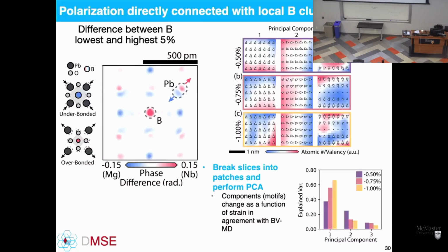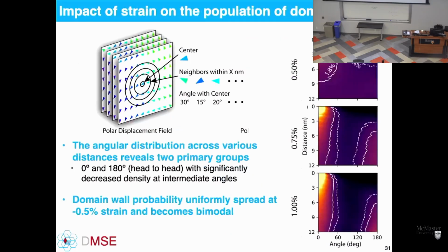And doing polar principal component analysis, for example, allows us to, in a statistical way, look at how these polar motifs, if you will, change across a sample. And as you increase in strain, you become more polar along a single direction, whereas the 0.5% strain, lower strain states, still preserve more of the sources of polarization that you can find locally around niobium and magnesium.